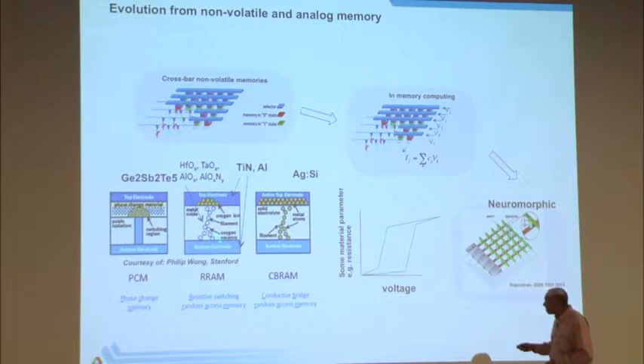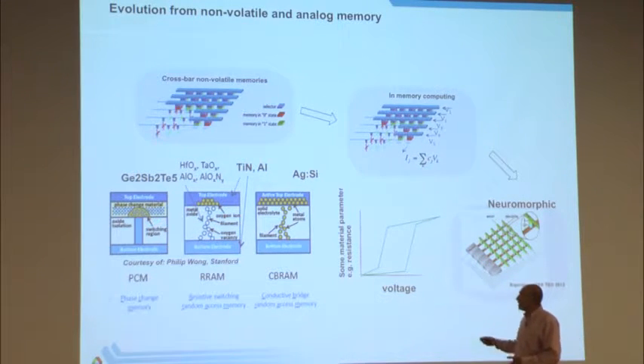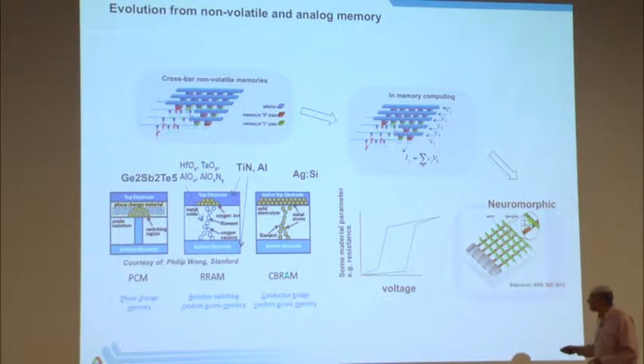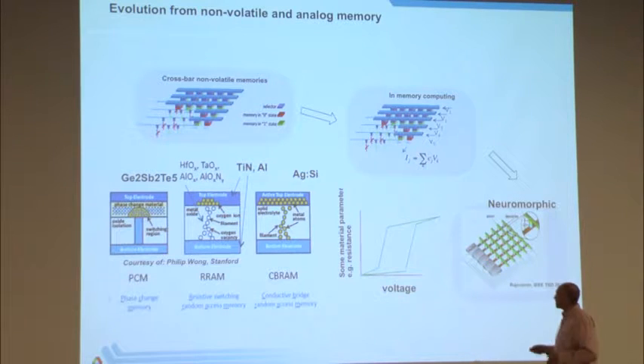In a resistive RAM, you have a material with two types of metal electrodes, and you put a bias. There's some oxygen vacancy redistribution, and its resistance changes. Conductive bridge RAM is similar, but it's considered to be a little electrochemical cell. You have something like copper with a dielectric and a bottom inert electrode. You apply a voltage. The copper forms a conducting filament. You can erase that filament by applying a reverse voltage, but that's your memory state, right?